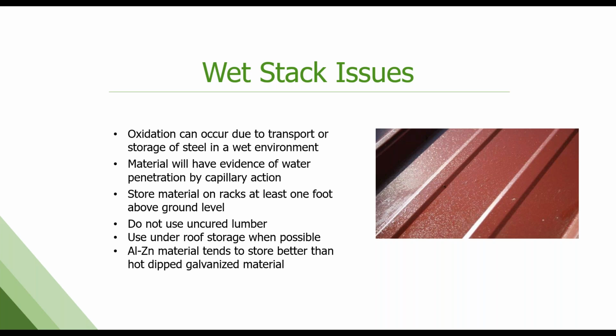Wet stack corrosion or storage corrosion. This is oxidation that occurs due to transport or storage in a wet environment. So if there's no airflow and water gets between these panels when they're stacked, it causes the substrate underneath to start forming an oxide product, which then pushes the paint off of the surface. There's a lot of information on how to store properly to prevent this out there in the industry, both at NCCA and most of the panel suppliers have technical bulletins on the best way to store product. The Galvalume product tends to hold up a little bit better than galvanized to this, but if conditions are right, if it's humid and warm and there's moisture, this can happen within a matter of a few days or a week out in the field. It's a big issue. Next.